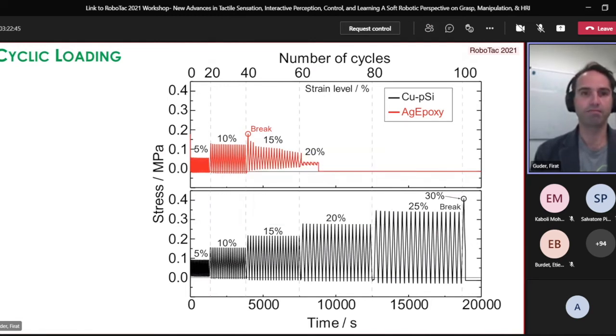And when we cycle these materials, we also see that after 15% strain, the silver epoxy contact fails, and the copper porous silicon contact does not fail essentially all the way up to 30% strain in cyclic loading. And then when it fails, it just fails completely.